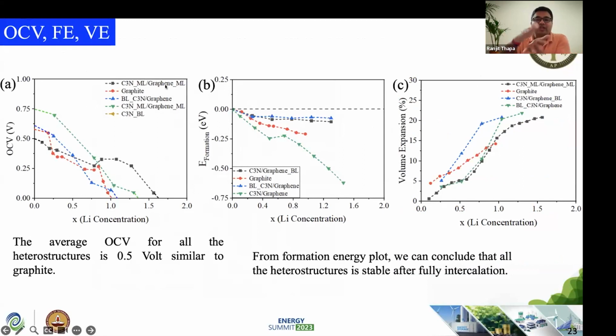Of course, it is a theoretical point of view. You can say experimentalist means 50-50. If there is layer by layer interactions, then your OCV will be within the range of 0.4. That is the demand of the industry, because you should not increase OCV more than 0.6, 0.7 like that. And formation energy is quite well for this black curve, and your volume expansion is also very low. So overall, it is showing that this also could be one of the materials which experimentalists are trying or could try more in the lab.